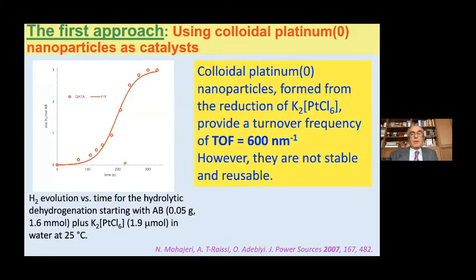So the first approach is the use of platinum nanoparticles, colloidal platinum nanoparticles as catalysts. So colloidal nanoparticles are active catalysts because of the large surface area of colloidal particles. So because of the large fraction of surface atoms, so that large fraction of the active sites, and therefore colloidal nanoparticles are usually much more active than compared to the bulk metal. So the first try was done in 2007.